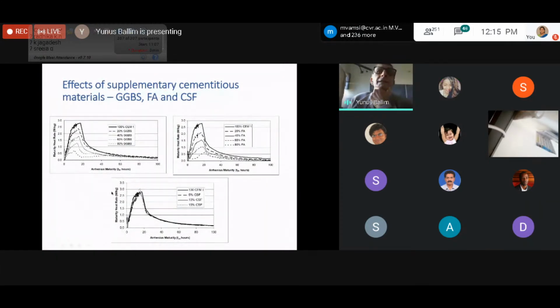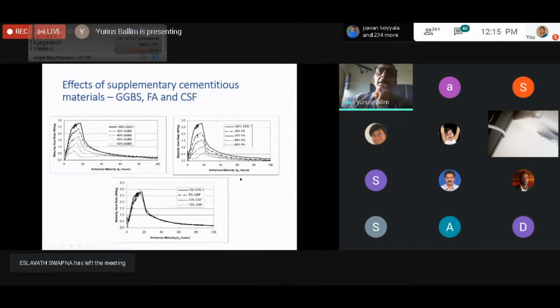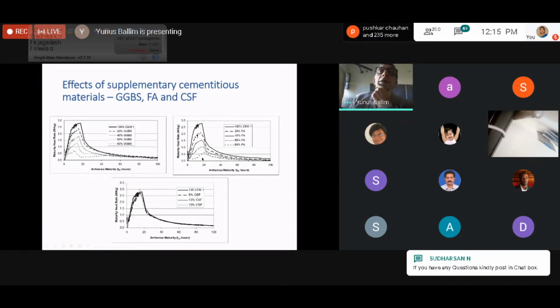Just the effect of some supplementary cementitious materials, slags going from 80% GGBS to 0% GGBS, 100% cement. And you can see the very significant effect on heat rate. Interesting that with fly ash, it has a similar effect in reducing heat rate, but it also delays slightly the peak heat rate. That's very interesting. And as expected, silica fume has almost no effect on heat rate.